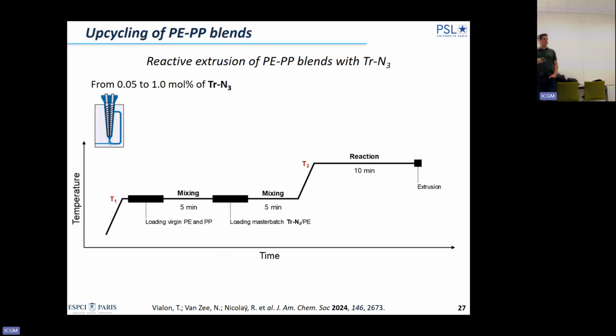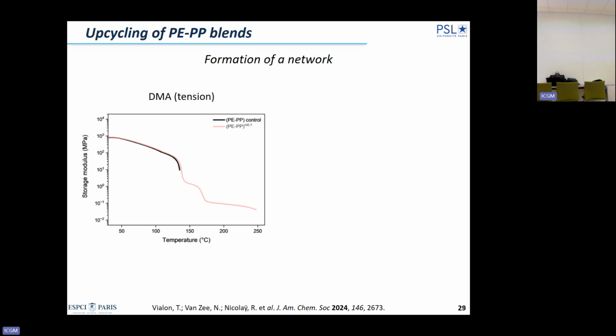And I will finish with this. Now we can blend PE and PP using the same additive at 1 mole%. We load both materials, then we introduce our additive, and then we heat to the processing temperature, which is exactly the same, and we do the extrusion. And in this case, if we look at the DMA, so this is the DMA of the blend of PE and PP, 70% in weight of PE, 30% in weight of PP. By DMA, if you look at the elastic modulus, when we reach the melting temperature of PE, which is the majority phase, the material flows under its own weight, as you would expect.